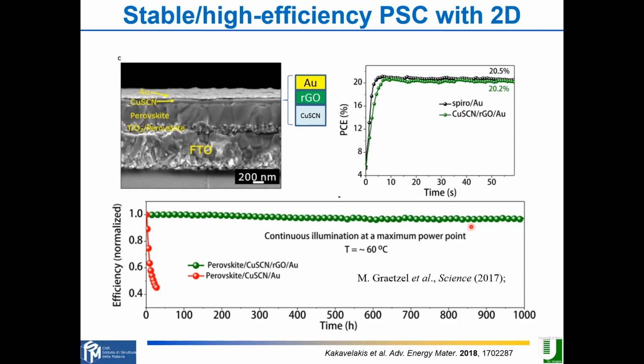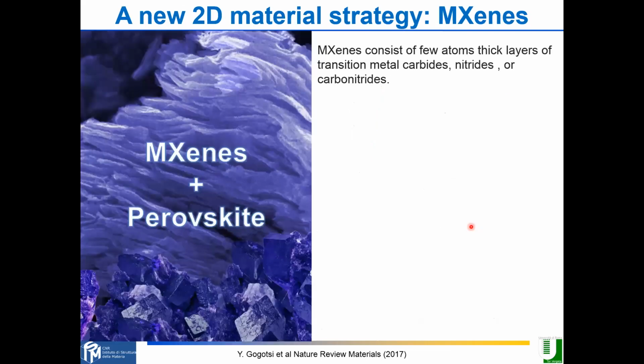So you can control even the ion migrations at the interface. Even gold could migrate into the perovskite, and this will degrade it. By putting this network of 2D material, you can stop this kind of degradation. So also for stability, this is very, very important.